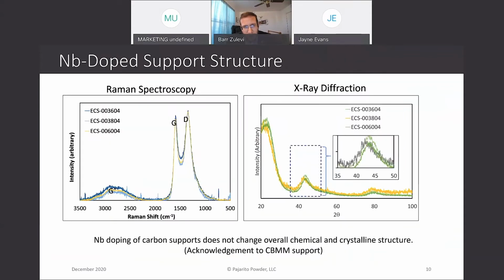When we look at some of the niobium-doped supports that we made with support from CBMM, we see here in a Raman spectroscopy, the carbon structure doesn't really differ from the base materials. The X-ray diffraction that gives you a measure of the crystallinity of the material is also not greatly affected, but you do see some variations depending on the structure and the amount and how the niobium is doped.